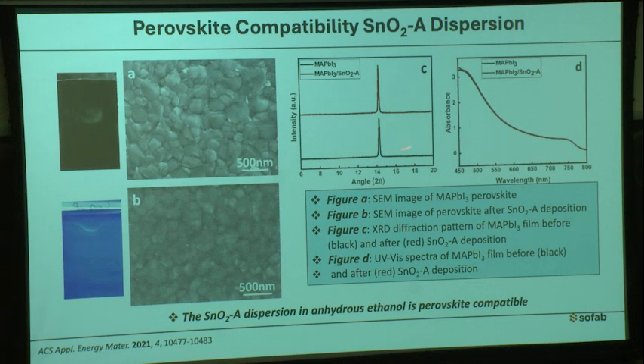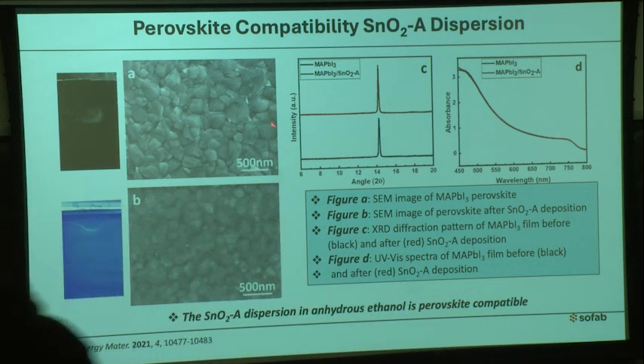After that, we characterize it using X-ray diffraction. This is the X-ray diffraction pattern of the perovskite, before tin oxide deposition, and this is after tin oxide deposition.